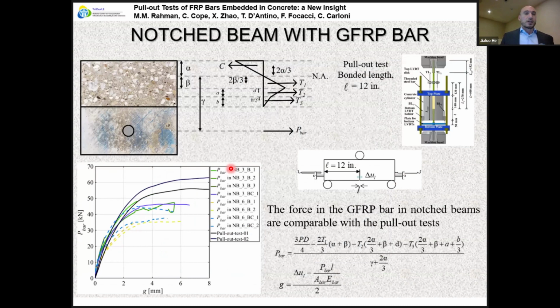So if you do a little bit of cross-section analysis using the data from DIC and simple equilibrium, you can get at any point of your response the load, the force in the bar. And then from DIC, if you want, you can get right at the level of the bar the opening of the crack. And the opening of the crack, except for the very small elastic deformation of the bar, divided by 2 is the slip of the bar when the crack opens.